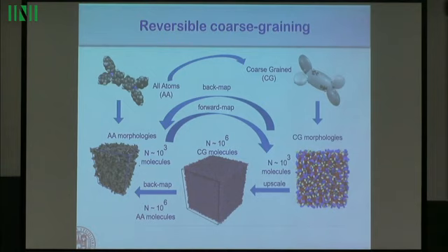And then we coarse grain in a parallel way, dividing the molecule. There's more than one way of doing it, but dividing it with some common chemical sense into bits, and these bits will be free to rotate according to a certain potential that we have to define. And we make again a simulation of the same order. We can use this to check that the parameters we have used are okay. When we are satisfied, we can upscale and simulate big samples of the order of 1 million molecules that you could not do by atomistic.